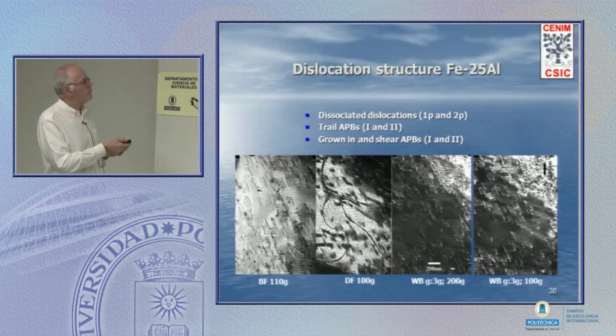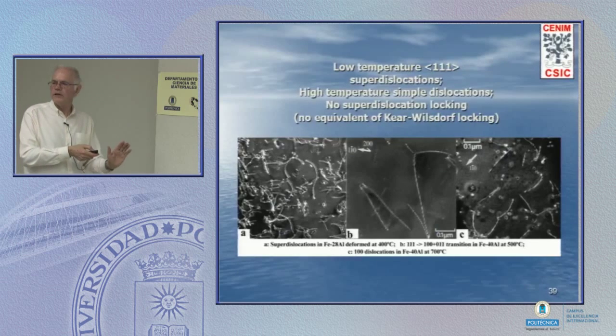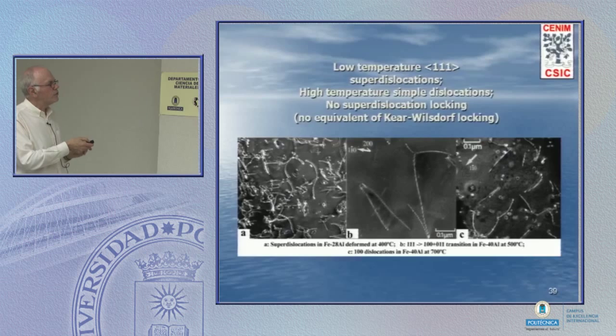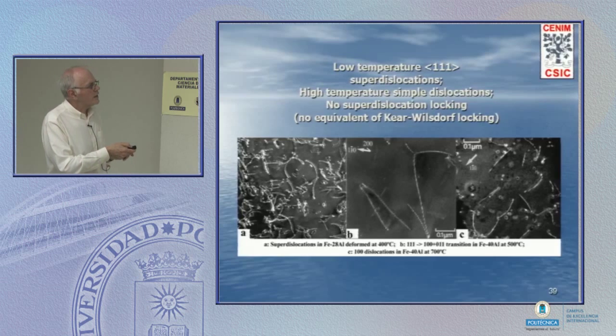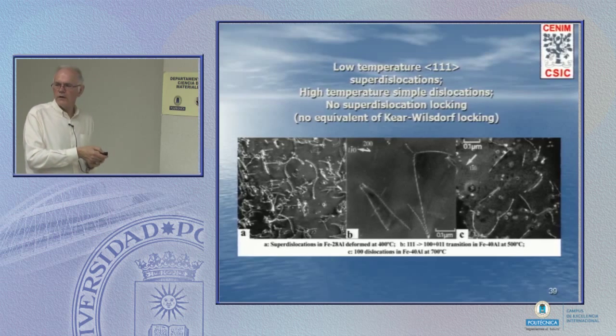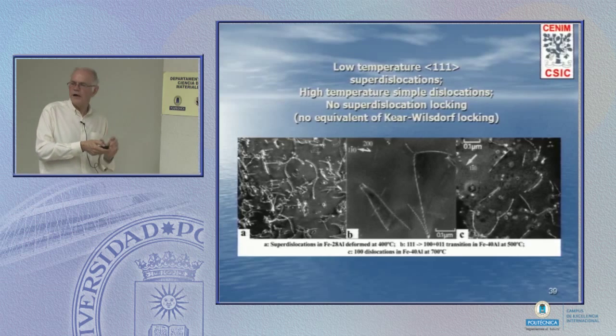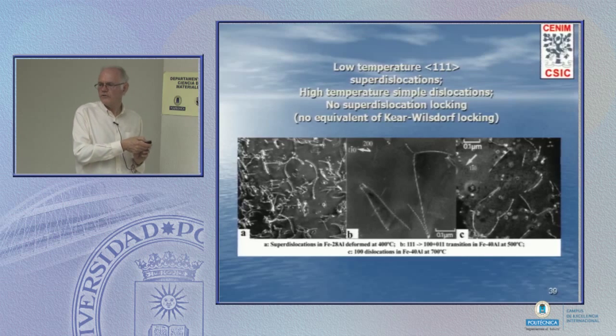Now if I go into the FeAl region, higher aluminium than Fe3Al, again I've got paired dislocations. I hope you can see these pairs, they're superdislocations. But of great interest is that these can react together and can decompose. They're very complicated dislocations. And here I've got something like a Burgers 1 dislocation and a Burgers 2 dislocation reacting to produce a Burgers 3. And that is a little node that cannot be moved in any direction. So it's an additional type of obstacle.